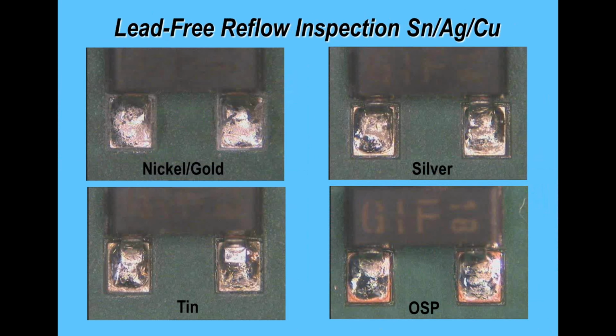Well, it's normal for these types of finishes, unless you overprint with solder paste or you print with a lower pad reduction area in your stencil. You can of course go to nitrogen, which will improve the results, but is that actually improving the quality? It's really just improving the visual appearance of the solder joint. Now by changing the profile for a particular paste, you may again improve the performance, but you're not really going to have a marked improvement, I would suggest.